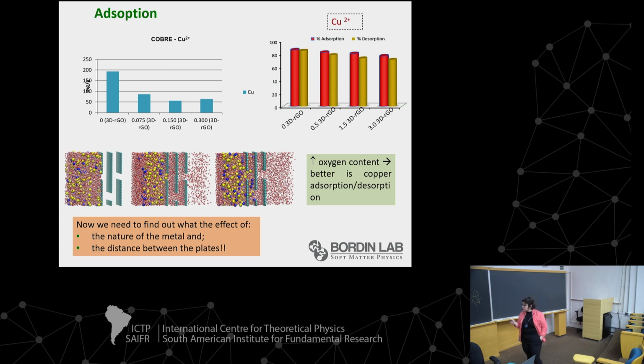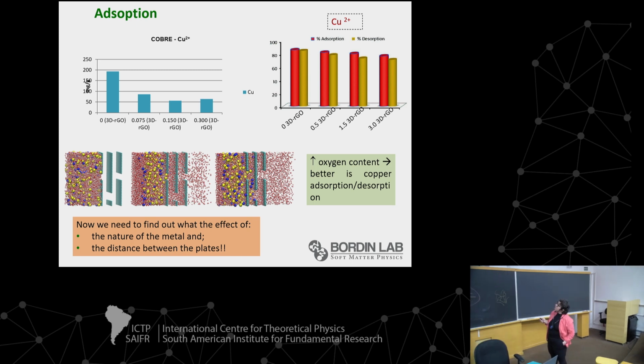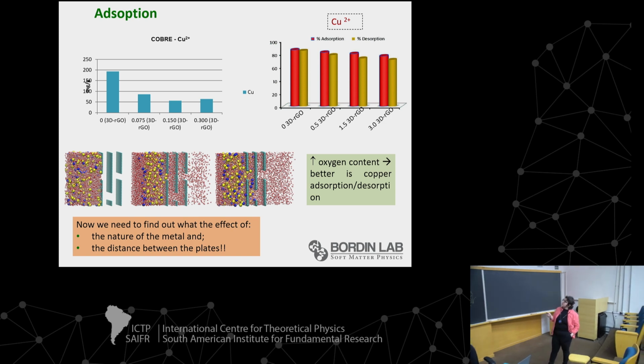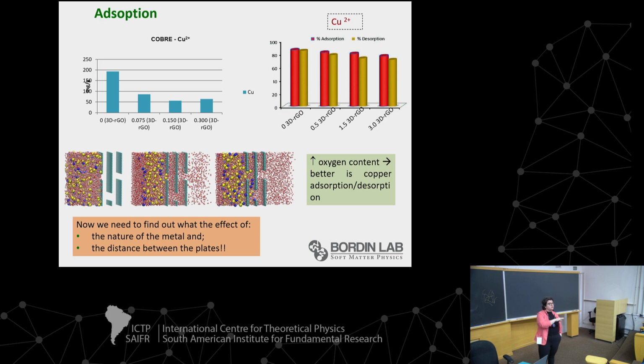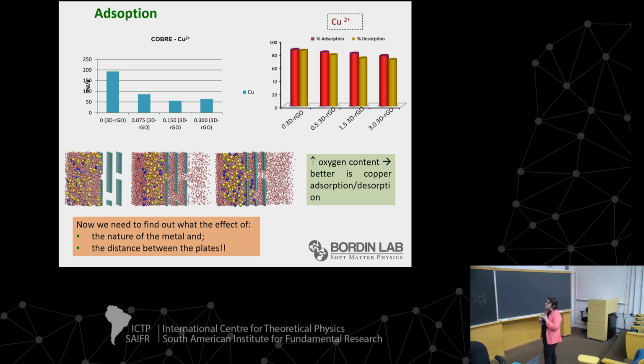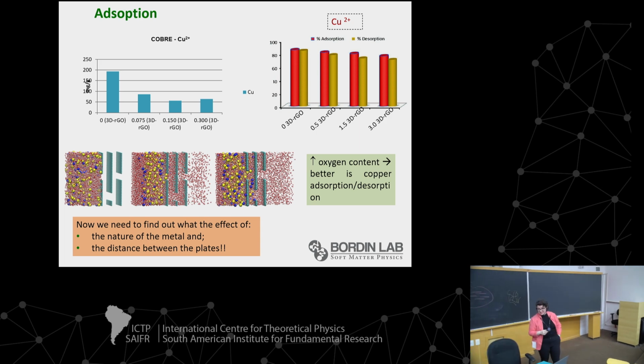Bordin did some calculations to explain for copper, and we saw when we increase the oxygen contents, the absorption and desorption on copper are better. This is an important thing, not only absorption, but the desorption to recover the material is a requirement for a real application. But now, Rafa, we need to find out what the effect is of the nature of the metal and the distance between the plates.